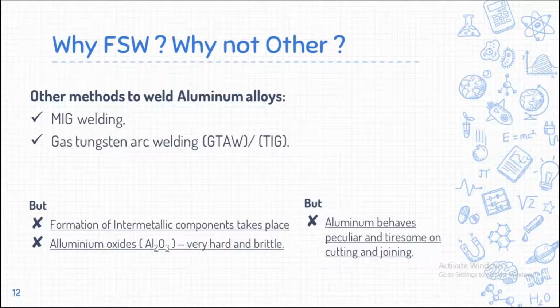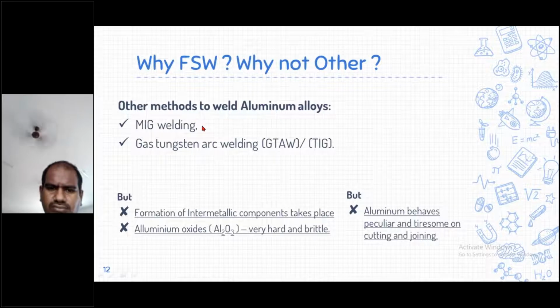Why only friction stir welding? Why not other welding processes? Particularly, this process is considered for non-ferrous materials like aluminum alloys. These aluminum alloys can also be welded by using conventional welding techniques like MIG welding, gas tungsten arc welding or TIG welding. These processes are also alternatives to weld these aluminum alloys. But using these conventional welding techniques, what happens here? These aluminum plates will be melted to weld in this particular process.